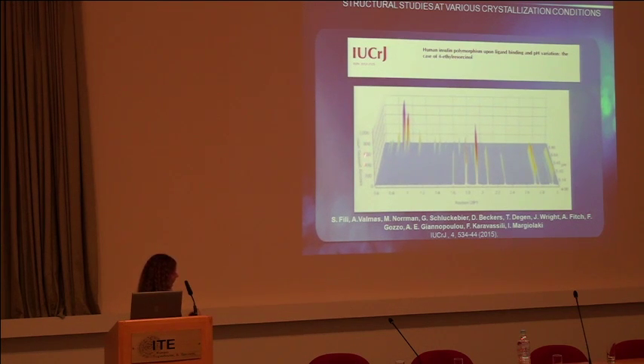We collected powder diffraction data. On this axis it's the intensity, on the horizontal axis is the 2 theta angle. So these are all the data we collected in less than 1 hour at the synchrotron. And for the non-powder diffractionists, from the diffraction peak positions, we extract space group and lattice parameters. From the intensities, we extract the atomic positions based on the electron density maps.